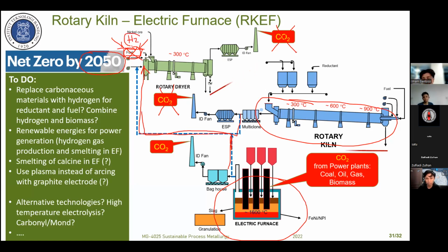If fuel is required, we should look at other sources of fuel, for example hydrogen. I think a hydrogen burner has already been developed in Germany for rotary kilns. We can install a hydrogen burner and use it as a source of energy if the energy from the off gas is not enough to dry the ore in the rotary dryer. In this case, we can also replace the fuel with hydrogen, and we use hydrogen here as a reductant. We should not burn all of the hydrogen from the burner, and we should also add more hydrogen to the side lance here to supply the condition for the reduction.